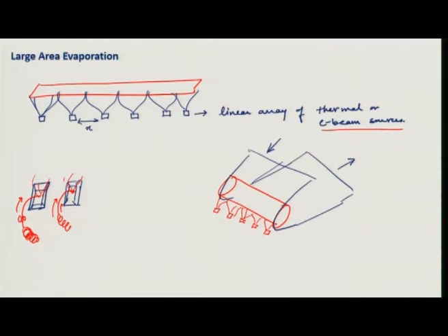And you can adjust the thickness of the film by adjusting the rate of pull of this flexible substrate, which is usually called a web. So, the pull of the web, and also the feed rate of the wire into these boats, which are kept at a constant temperature. Okay. And you can also do inline monitoring, and you can adjust the temperature of these crucibles to have a more uniform deposition across the width of the web.